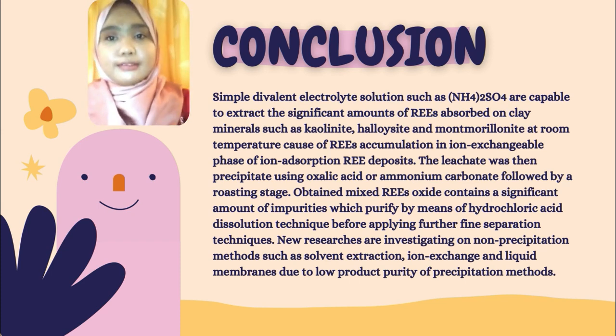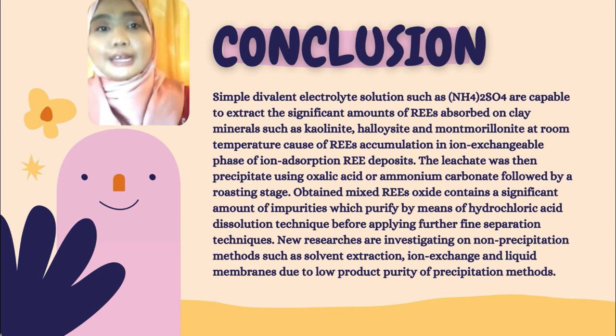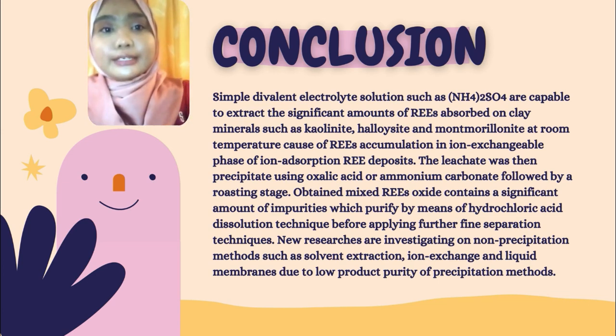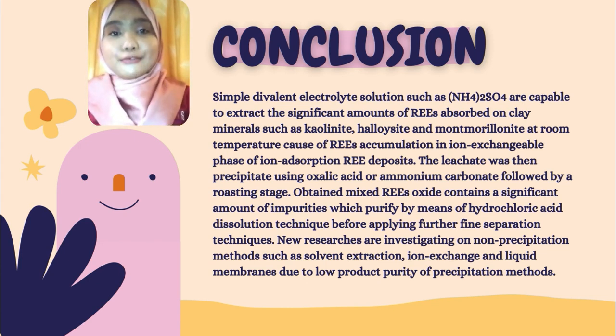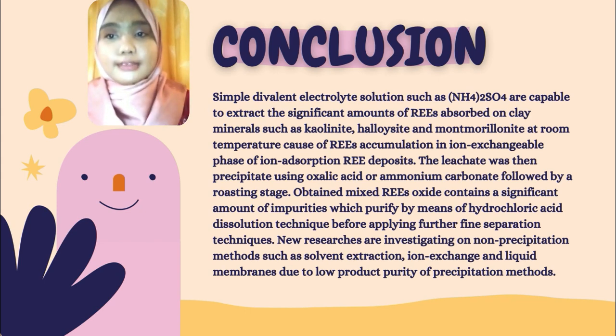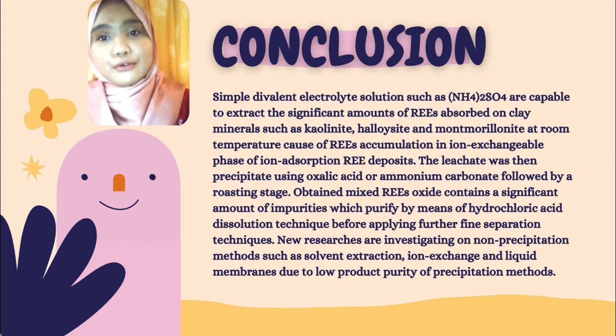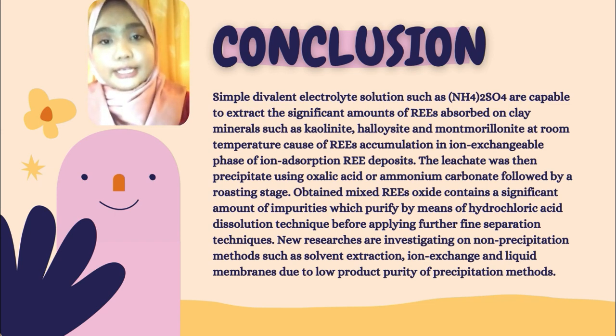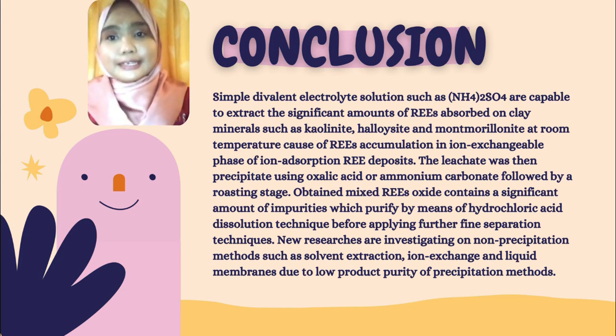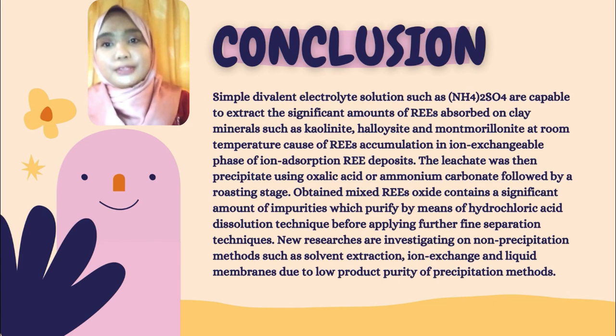The leachate was then precipitated using oxalic acid or ammonium carbonate, followed by a roasting stage. From in situ leaching method, we obtained that mixed REE oxide contains a significant amount of impurities, which are purified by means of hydrochloric acid dissolution technique before applying further fine separation technique. New researchers are investigating non-precipitation methods such as solvent extraction, ion exchange and liquid membranes due to low product purity of precipitation methods.